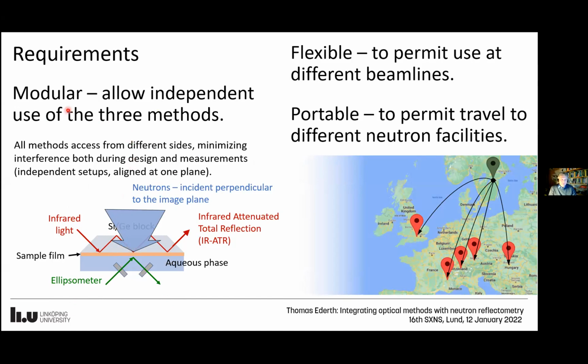And the modularity is related to the flexibility. We wanted this to be a setup that could be used at different beamlines, so it should be relatively easy to rearrange. And we wanted this to be portable. We found that we were using experiments at different beamlines, and we did not really want to be stuck with one facility or one beamline for experiments, but rather have the flexibility to do this at different places.